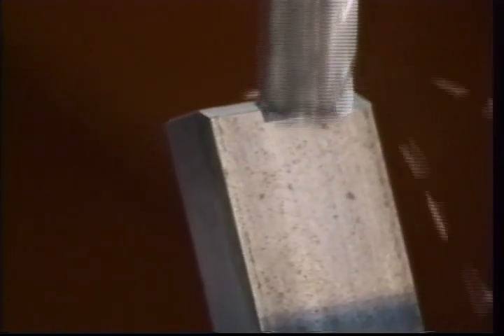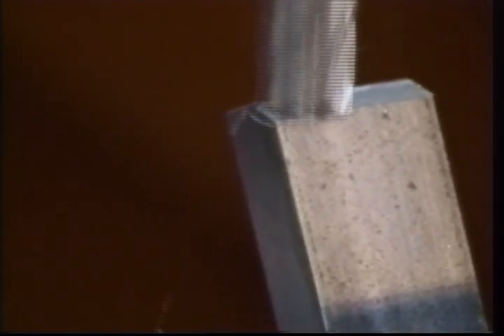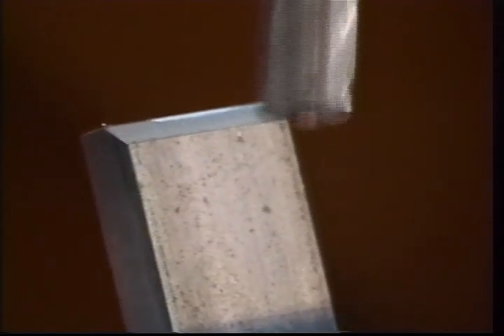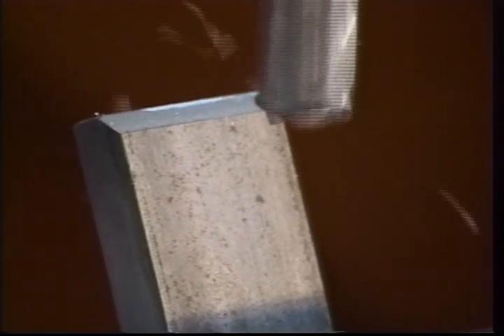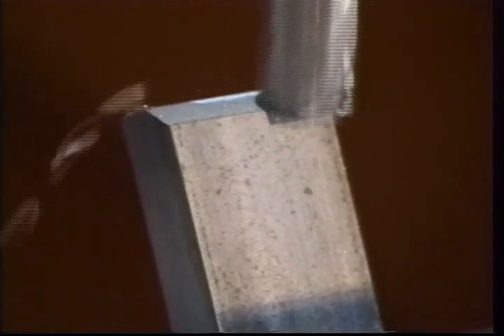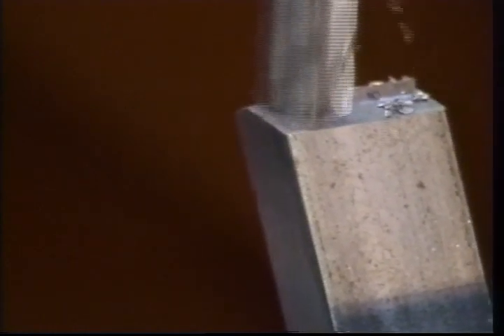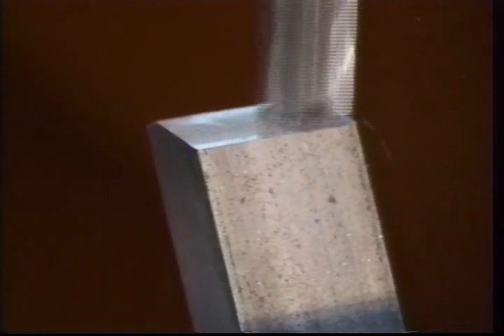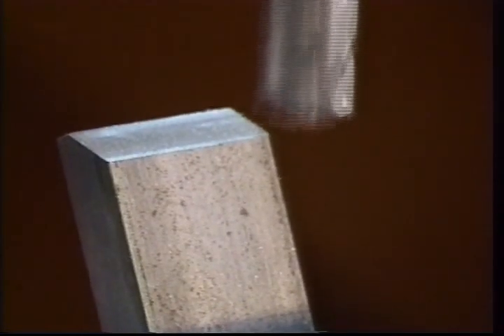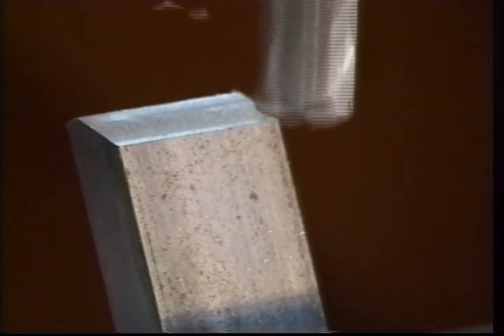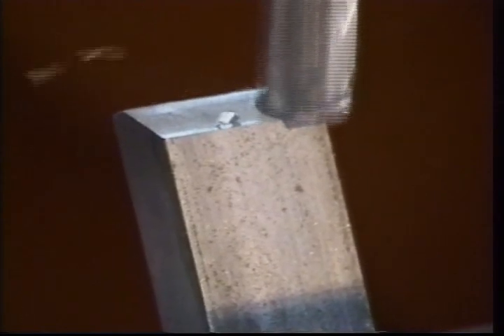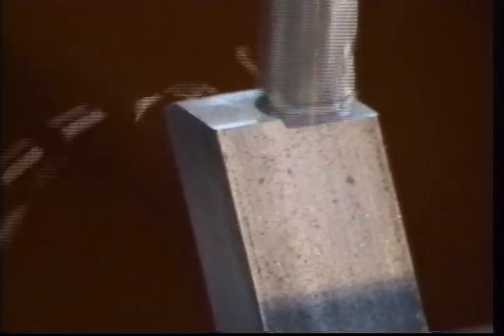Again, listen to the machine. We've got a nice smooth sound as the cutter is working across the part. It's not going clackety clackety clack, indicating that we're machining at too high of an RPM or too fast of a feed rate. When you have a lot of material exposed, as in this case, you want to have a very slow feed rate. We don't want to hog across it really quick, tearing the part from the vise. We're just about there, and remember, this is kind of a climb operation relative to the top edge of the part. We're removing the burr off in this process.